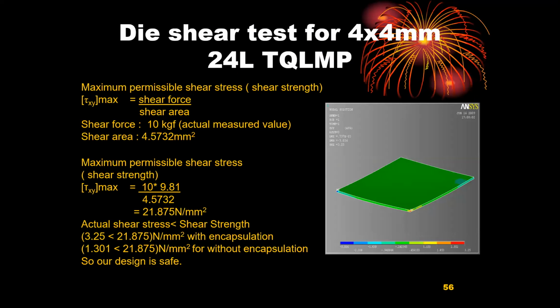Coming to a simple failure analysis exercise with the die shear test for a 24L TQLMP test. This was done for almost all the ICs, but I'm just showing a few examples of how the procedure went on. So the maximum permissible shear stress was about 21.875 MPa, or Newton per mm squared, for a shear area. With a shear force of 10 kilogram force that was used, the actual shear stress was much lesser than the shear strength. So we were happy that even at MOT, or say 25 degrees Celsius, or any temperature in between, our die and the copper lead frame were absolutely safe.